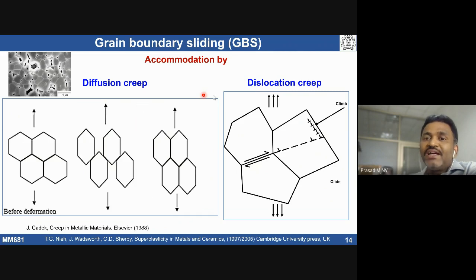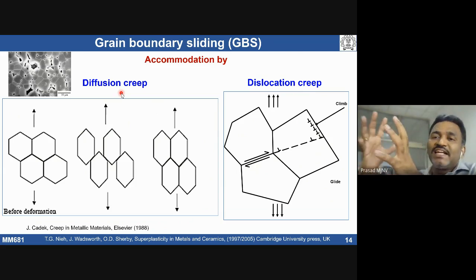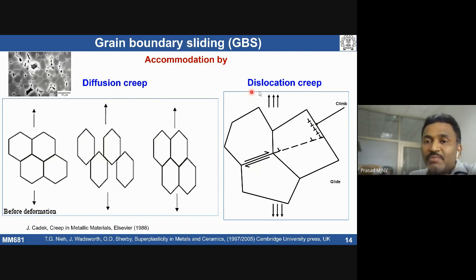So depending on initial grain size, if the grain size is finer, typically subgrains are going to form. That is going to control the grain boundary sliding cavity formation, as compared to coarse grain materials. We need to have fine grains. Again, within that, if we talk about 1 micrometer, 10 micrometer, a 1 micrometer grain size can undergo this kind of grain boundary sliding with diffusion creep accommodation. 10 micrometer grain size will undergo dislocation creep accommodation of the grain boundary sliding. It's the initial grain size present at the temperature that makes a difference, what type of creep mechanism is going to accommodate the grain boundary sliding.